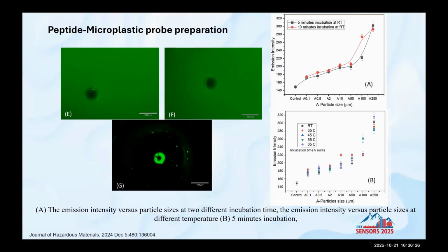As the fluorescence microscopy images show, these particles, spherical in shape, are the intentionally added polystyrene particles we added to water sources, and we mixed them with the peptide sources tagged with fluorescence. As you see, the peptides are just bonded around this microplastic, and because of the fluorescence tag, we can distinguish them on the fluorescence microscopy.